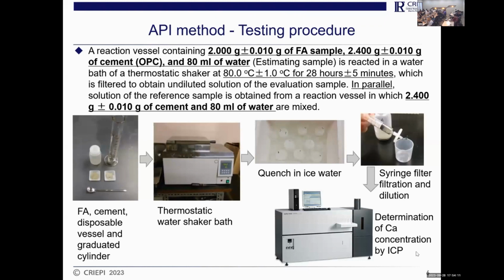By the way, my testing method, the API testing procedure, is like this. Use a small plastic container, and the amount of sample is 2 grams of fly ash and 2.4 grams of cement. We use the ordinary type one, and mix it with 80 milliliters of purified water. And the reaction condition is like this: 80 centigrade, kept for 28 hours.